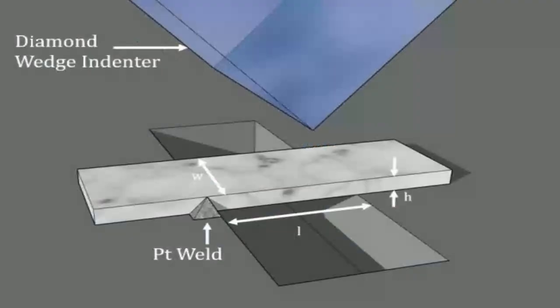The DCB test geometry, combined with doing it in-situ, meaning inside the SEM while watching, allows for slow, stable crack growth over a much longer distance. You can literally watch the crack interact with the microstructure in real time under the microscope, so you can see the bridging and deflection happening. Exactly, you directly observe those toughening mechanisms.